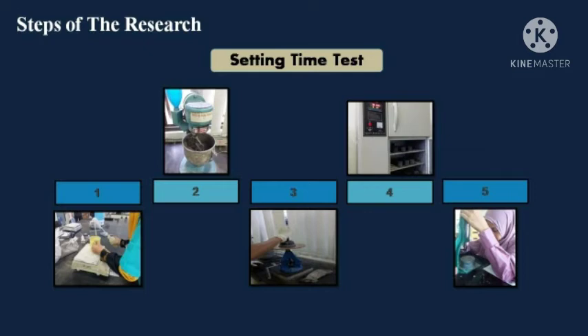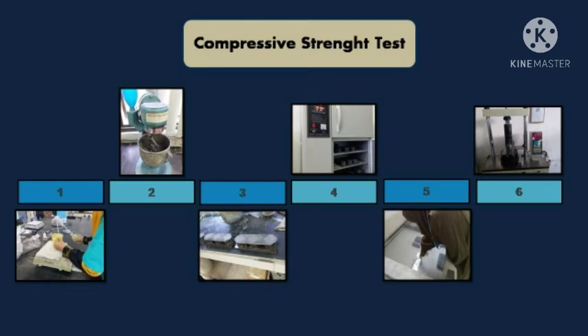In the setting time test, there are 5 steps, including weighing water and cement according to the specific portion, making cement paste with a cement mixer, determining normal consistency using a flow table, hardening the cement in a wet box, and testing setting time using a VICAT tool. And the second is the compressive strength test with 6 stages, including weighing water, cement, and silica sand according to the specific portion, making mortar with a cement mixer, printing cement mortar, hardening the cement in a wet box, and testing the compressive strength using a compressive strength tool.